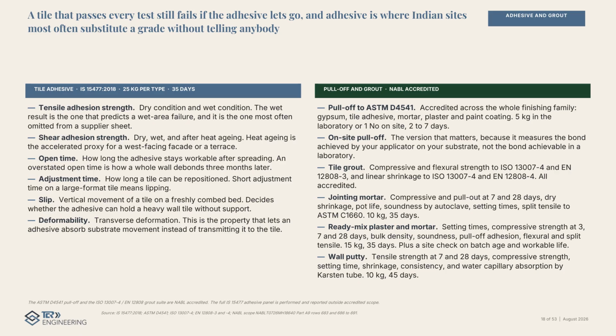A tile that passes every test still fails if the adhesive lets go. And adhesive is where Indian sites most often substitute a grade without telling anybody. The full panel under IS 15477 covers tensile and shear adhesion, dry, wet, and after heat aging, plus open time, adjustment time, slip, and deformability. 25 kilograms per type, 35 days. That panel sits outside our accredited scope, and we say so.